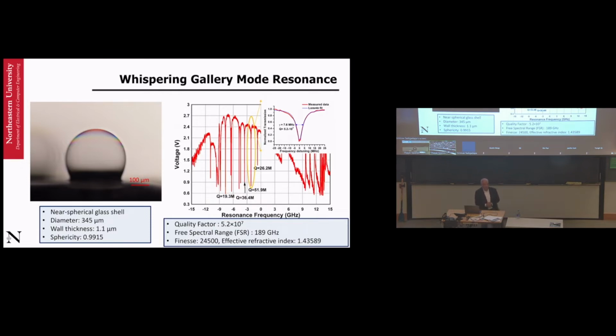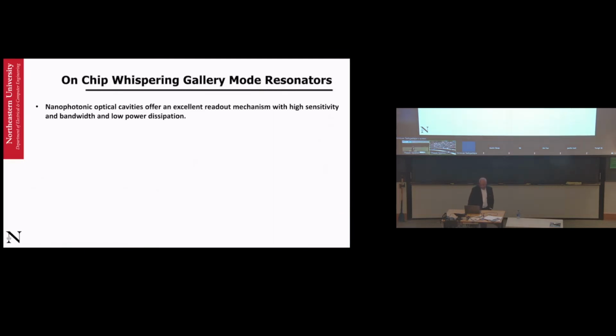Only optical devices have this type of Qs. If you have a mechanical system like the one I showed you at the beginning with the spring, or even a MEMS cantilever, getting a Q of 2,000 or 3,000 will be already quite a challenge, okay? So we need to be very careful about what Q is and how to optimize that. What this means is that the light goes around this little bubble for a distance of maybe about 47 meters before it dies. Basically, it's dissipated beyond that. 47 meters for a light that is only 1550 nanometers is quite impressive, or maybe in this case, 790 nanometers. So compared to its size, it travels a long way before it has gone away. That's the ring down time for these resonators.